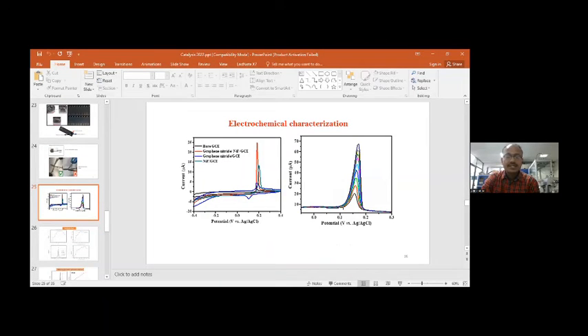And finally, we have taken that working electrode, that is the screen printed electrode, in the presence of mercury. In the presence of mercury, we found a very good response of this graphitic carbon nitride nickel ferrite screen printed electrode. So this clearly shows that the modified electrode has shown a very good response towards mercury. Then, by using cyclic voltammetry, we performed this experiment in order to quantify it. We have done anodic stripping voltammetry, as I previously told how it works. With increasing mercury concentration from 10 to 100 ppb, the response increased, and we got 2.35 ppb as the limit of detection.